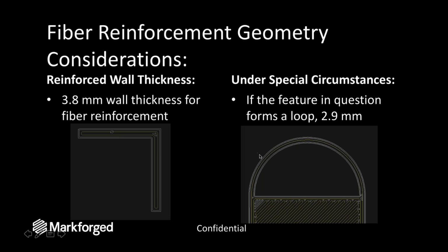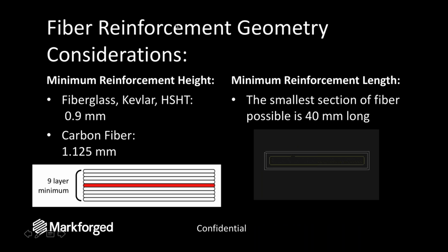There are exceptions to that. For example, on the right here, we're able to fit one strand of fiber inside of this loop extrusion because it can loop back in with the rest of the part. So if the feature is able to form a loop, then you can create a 2.9 millimeter wall. If not, then stick with 3.8 millimeters, and that will guarantee that fiber is able to fit into your part. Because we're laying down fiber on the inside of the parts, the fiber has a minimum required length. It has to be 40 millimeters or longer to be able to fit inside of your part. And so that means that when it comes to very, very small features, fiber may not be able to fit. And that's a big consideration in our printers.